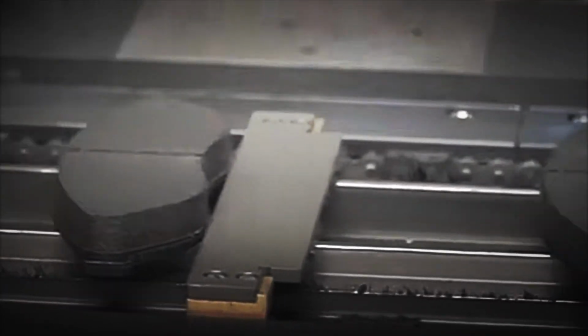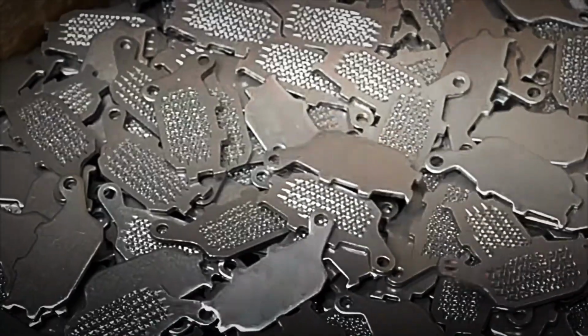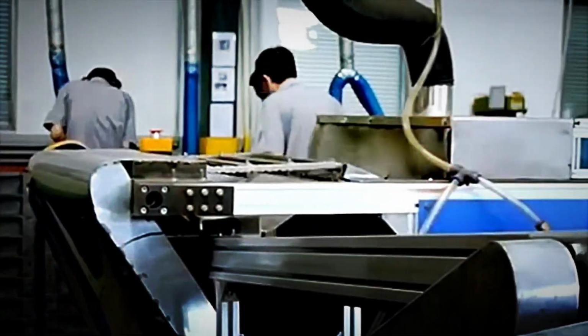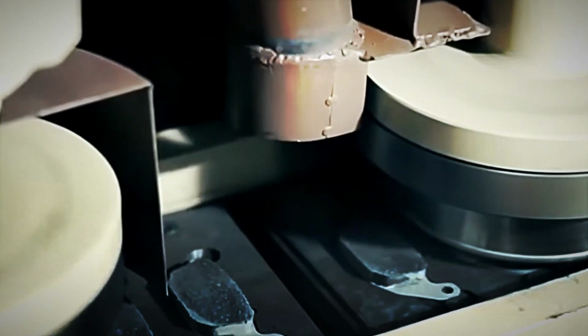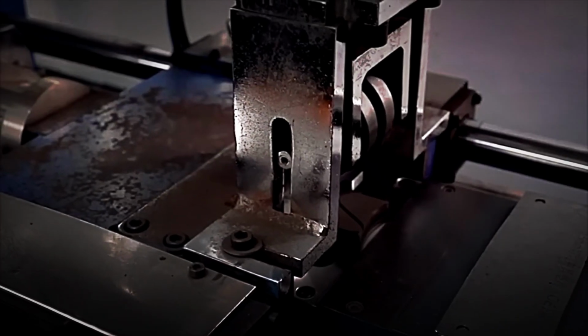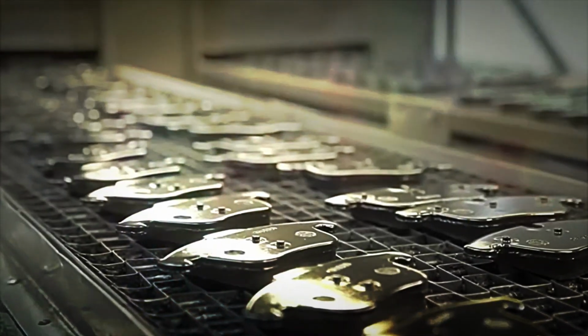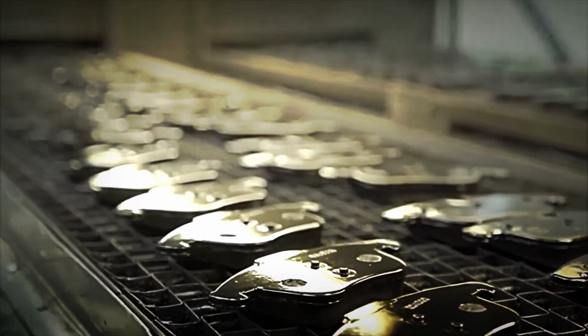This furnace is usually a long tunnel, where the pads move forward slowly while passing through different temperature zones. The heating is not abrupt, because a sudden increase could generate internal stresses and cracks. The temperature rises progressively until it reaches very high values, close to the actual operating range of the pad. For several hours, the material remains in that controlled environment, allowing the ceramic structure to consolidate, the metallic fibers to integrate firmly, and the graphite and other additives to stabilize within the matrix. Sintering is the step that transforms a fragile block into a component capable of withstanding extreme conditions.